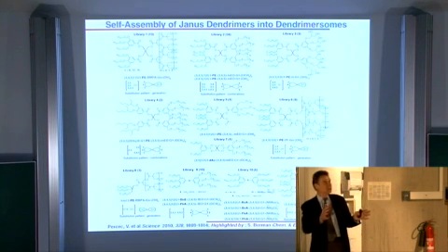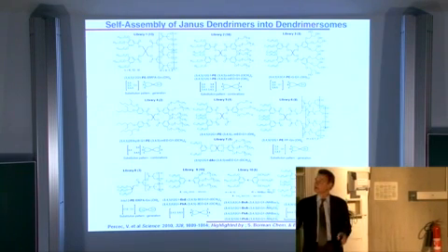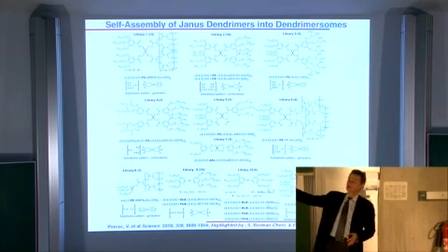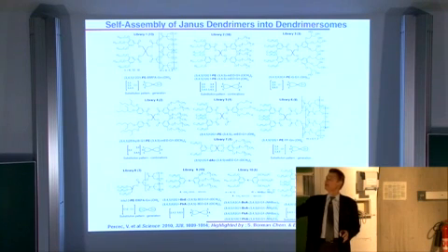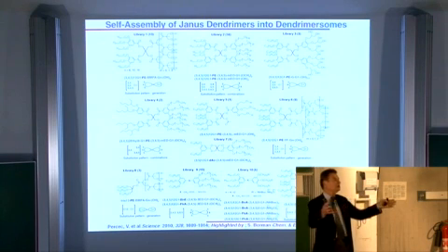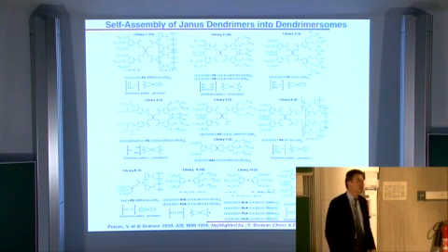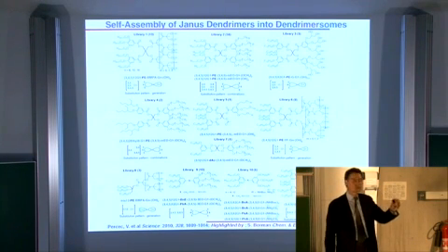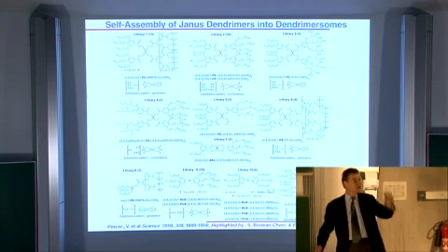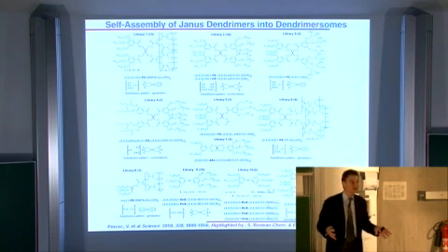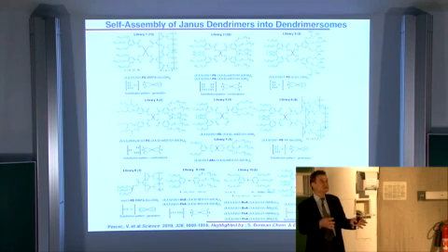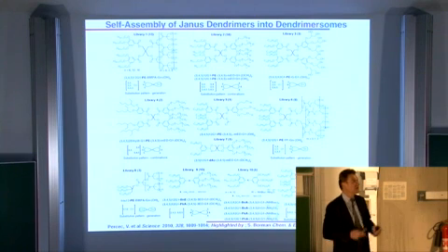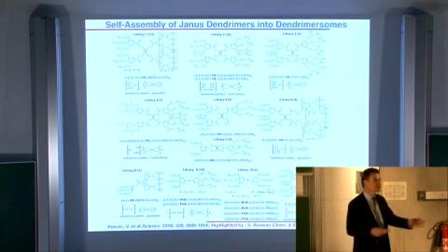We use an orthogonal approach to the synthesis of this molecule, so that if we make 5 different hydrophilic parts and 5 different hydrophobic parts, I'm not going to go into details, you can make immediately 25 Janus dendritic molecules. And we figured out that if you take an ethanol solution of any of these molecules and drop it in water, they spontaneously form vesicles. And those vesicles are monodispersed, by a combination of light scattering and cryomicroscopy. That was easy to do.